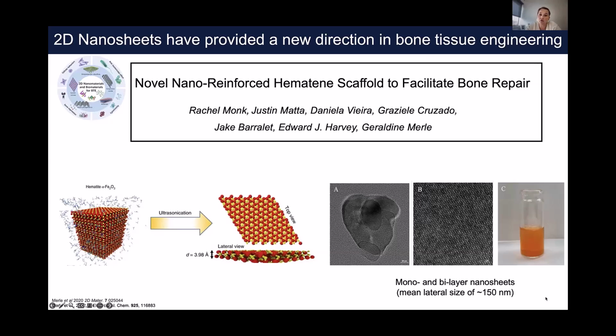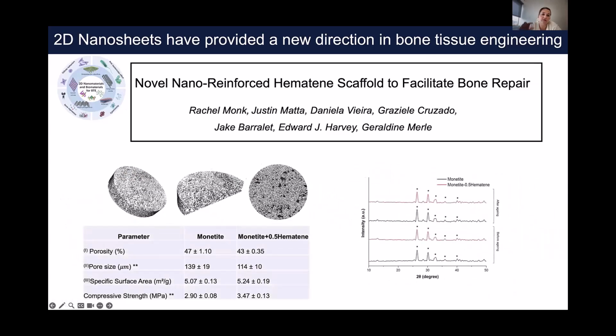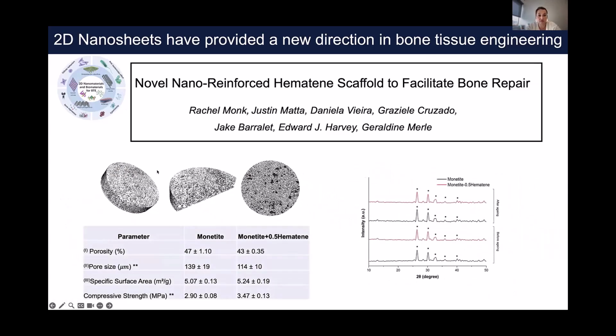What we did, we took that solution and she mixed it with some implants, some bioceramics. So you see that, first of all, the compressive strength increased, and the pore size decreased because you fill the porosity with your nanomaterial. Here it's an X-ray diffractogram to show that when you added the hematene, you didn't change the crystallinity of your implants. And then after that, we seeded cells on it to see if we could see some improvement by adding this 2D layer of iron oxide.